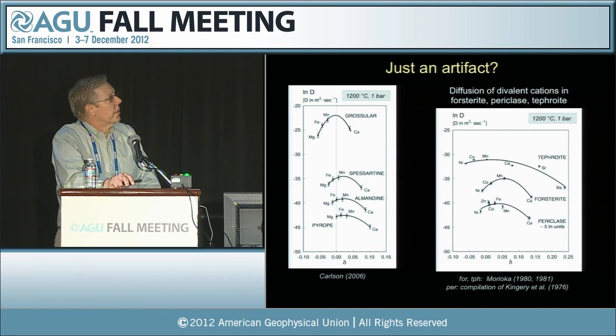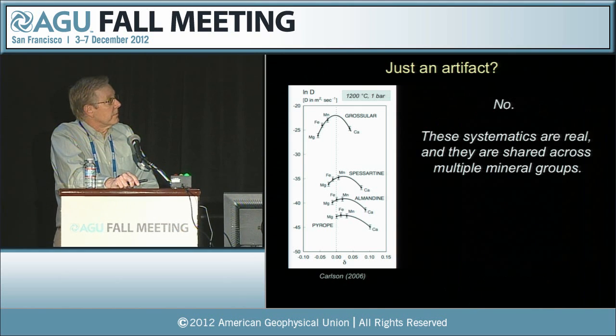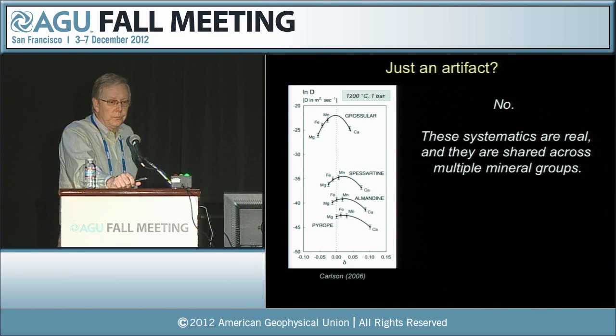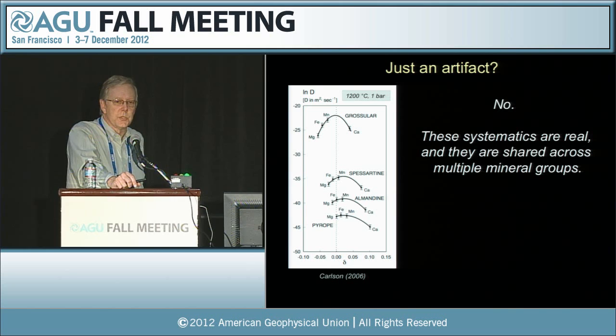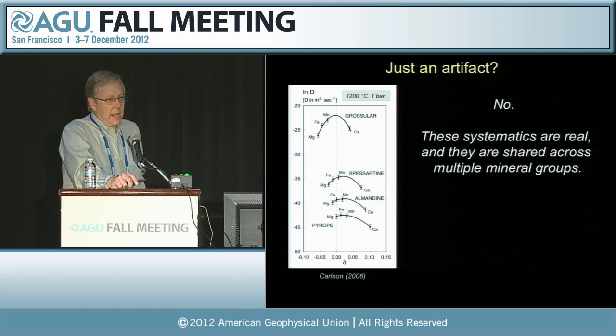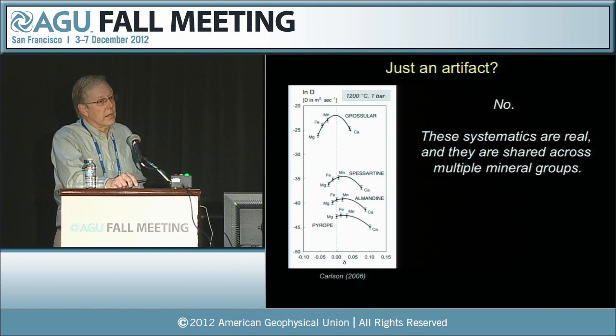We have data for forsterite, periclase, and tephroite, the manganese olivine, that behave very similarly to what we see in garnet. So I conclude that these systematics are real, that they're shared across multiple mineral groups, and that they are really highlighting a fundamental gap in our understanding of diffusion in ionic solids in general and in minerals in particular.